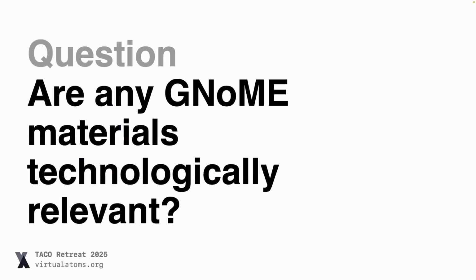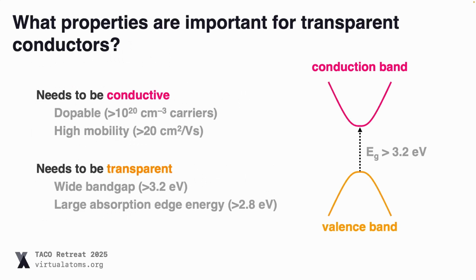So we wanted to look into this, because all they had done before was just look at the energies of these materials, nothing about the properties. So we wanted to know, are there any materials in this data set which are technologically relevant? The application that we were interested in is transparent conductors. You have them in your phone, for example, a transparent conducting oxide. These have the conflicting properties of needing to be transparent but also conductive at the same time. So they need to be dopable, but they also need to have a very wide band gap, about 3.2 electron volts. So with these measures of high mobility, high dopability, wide band gap in mind, we set about exploring the GNoME data set.